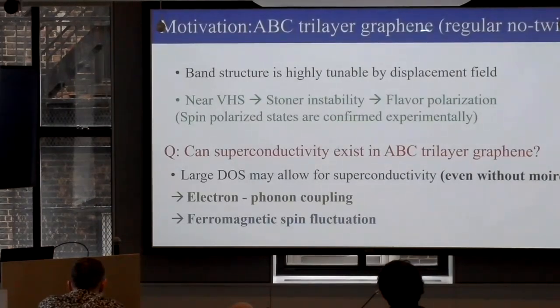This is seminal work because it shows that this feeling people had, Volovik has been talking about it for a long time, that graphene may be superconducting. And people have seen telltale signs that many big, thick layers of graphene are sometimes superconducting. There's something there. So this band structure is highly tunable by displacement field, by applying an electric field. And they find there is a lot of symmetry breaking here.